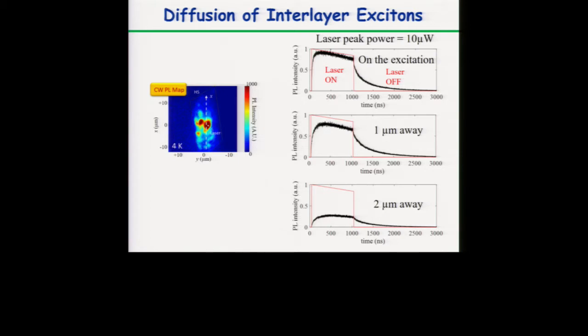So with these line cuts of time-dependent photoluminescence, we can now construct how long it takes for each of these points away from the excitation spot, and we can measure the diffusion constant. That's what I will mention in the next slide. So here's the same map, right? At high power, these excitons are repulsive. They diffuse because of this Coulomb interaction.